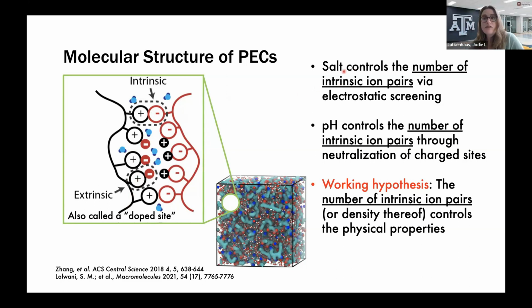So we can go into the lab and control the ratio of intrinsic and extrinsic ion pairs by changing the salt concentration. We can use salt to screen charge and break up intrinsic ion pairs as the salt is competing for ion pairing. We can also use pH to control the number of intrinsic ion pair crosslinks. Some of these polyelectrolytes are pH responsive.